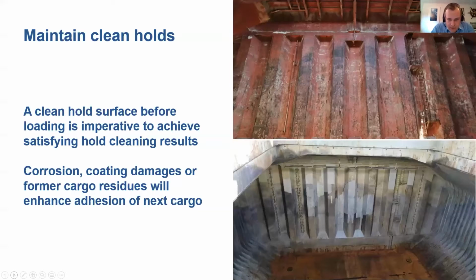What we see, often in holds, or quite often actually, are coatings that were damaged over time, or contaminated, not cleaned, or even overcoated by patch-up works with paint, where the surface has not been properly prepared. And if you see that on the lower picture, where you have a patch-up of paint on a surface that has not been properly prepared, the coating will not adhere to the surface, so it will peel off after a while, and then the doom loop starts over again, because the stains are getting uncovered, and you end up at the beginning where you started.